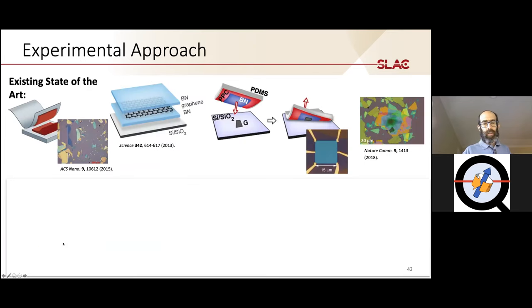And so the existing state of the art involves using stamps to pick up exfoliated flakes and stacking them. If you try to put tens of layers together, this one is, I think, 28 layers that took 20 hours with a robotic system built in Japan. But you can see it's a mess. It's going to be hard to do anything with it in terms of electronics, because there are so many other flakes around.